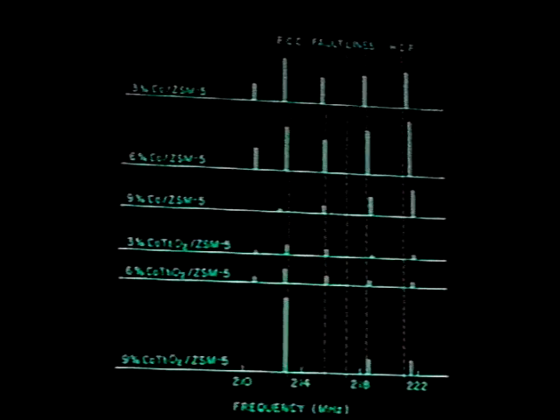In the case of the cobalt thoria samples, if you remember the previous spectrum, there were no HCP lines, but after being used as a catalyst, the HCP lines started appearing. There was again a reduction in the intensities of the FCC lines in the case of the cobalt thoria 3% and 6% samples, but there was an increase in the 9% samples.